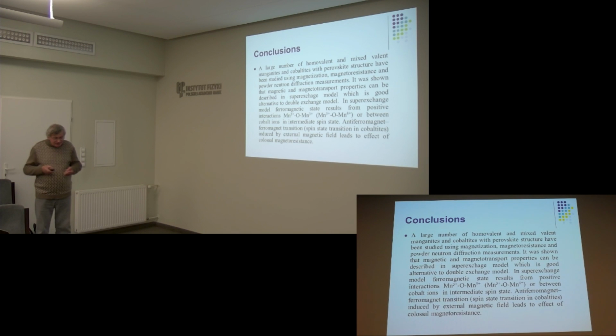I have had some discussion with John Goodenough. We have a common conclusion that the super exchange interaction is very important for mixed valence manganites, because in mixed valence manganites there is a very low density of charge carriers at the Fermi level. The majority of eg electrons are localized. These localized electrons transform the magnetic structure into ferromagnetic via super exchange,